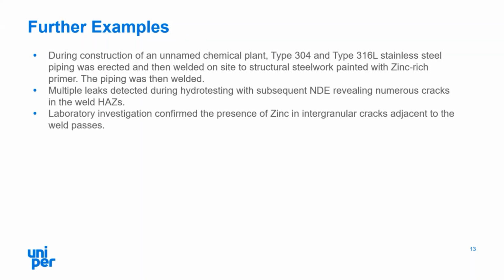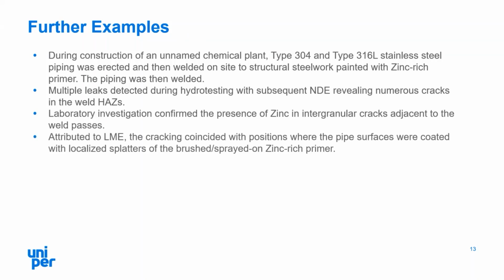The laboratory investigation confirmed zinc in the cracks adjacent to the weld passes, and the whole process itself was attributed to liquid metal embrittlement, similar to what we've previously described. The cracking coincided with positions where the stainless steel pipe surfaces had been coated with localized splatters from the brushed or sprayed on zinc-rich primer which had been used.